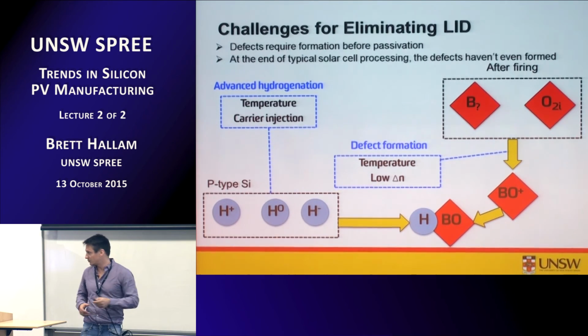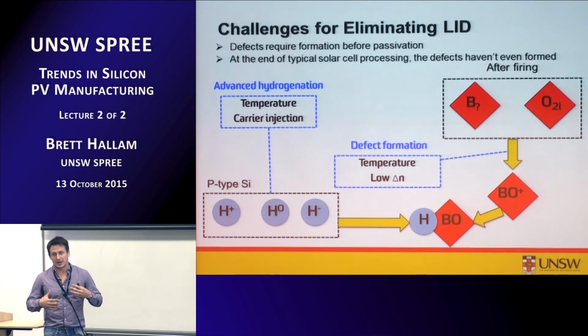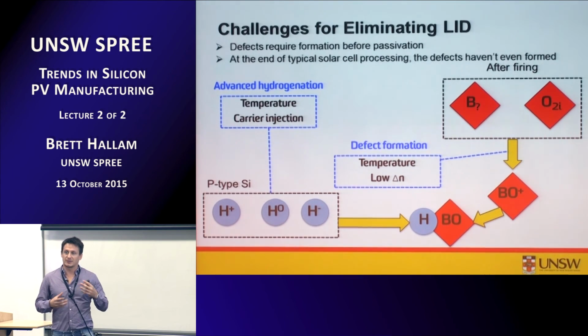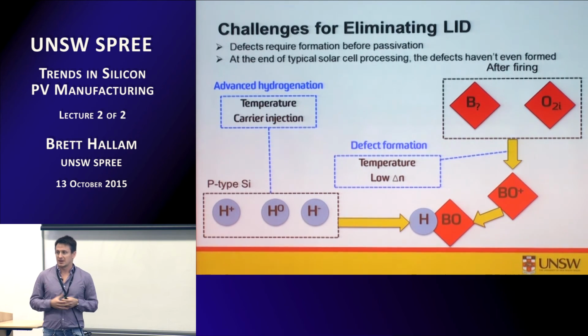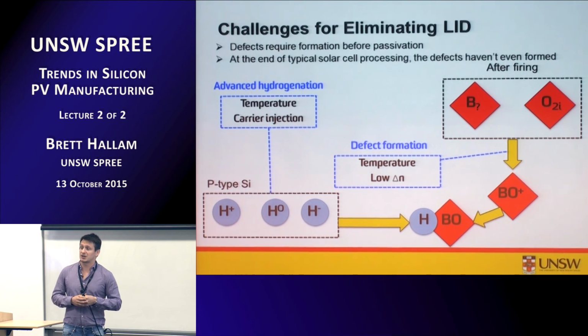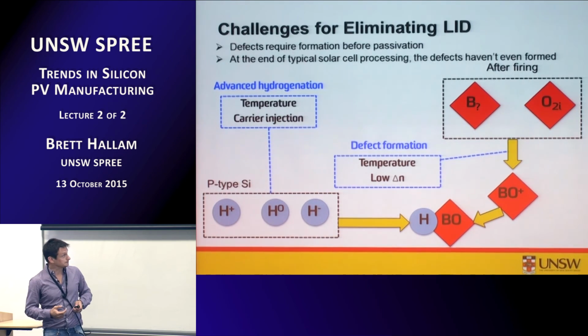And we've been doing quite a bit of work around this area. And from what our modelling has shown, it's really this availability of the defects which limits our ability to eliminate LID in the solar cells. And so a lot of the tools at the moment use relatively low illumination intensities, and it takes quite a long time. And it seems as though the key to solving that is to use substantially higher illumination intensities to actually increase the rate of the defect formation. So we can more effectively get rid of the problem by enhancing the formation of the defect.